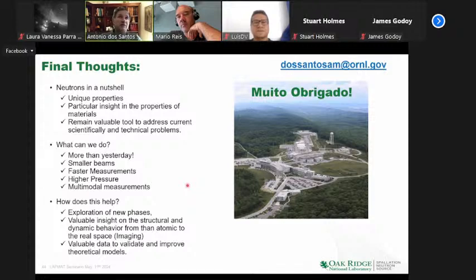There's a specific instrument for that. It's called a magnetic reflectometer. It does have polarized neutrons to really see because the samples are small, to get much more sensitivity to the moment and the direction. It does exist. I believe they have 5 Tesla magnets. They have at least a 1 Tesla permanent magnet. It then depends what they want to measure. If you want a fully polarized measurement of the interface, you actually don't want to apply a strong magnetic field. But if you do have a heterostructure and you want to polarize with field, that does exist as well. But it's a very specific instrument. And they have tried, and to be honest, I'm not sure how successful it was, to grow a thicker film and go to a single crystal diffractometer to see if they could just see that bulk. But of course, then it really depends. I'd love to talk with you if you have a specific idea.